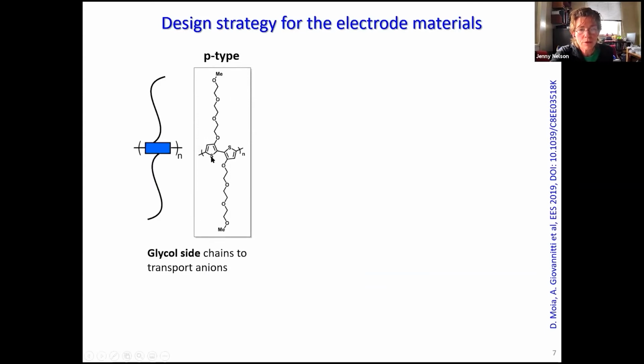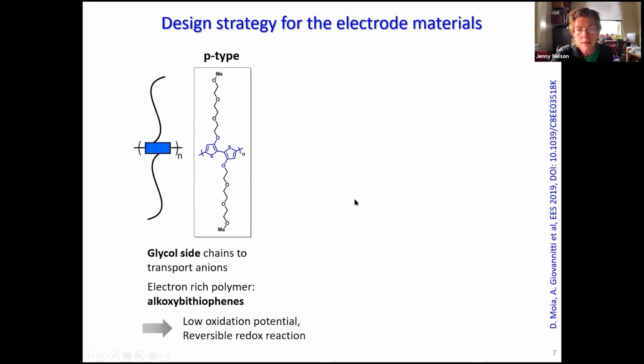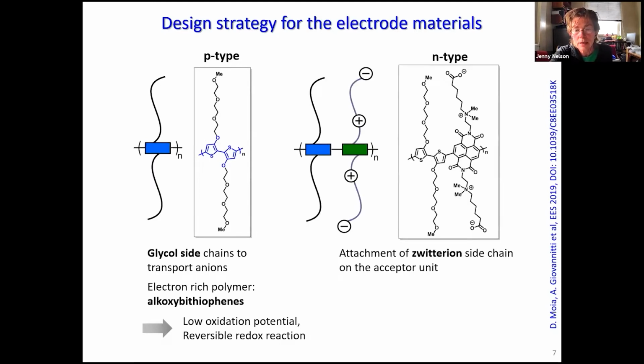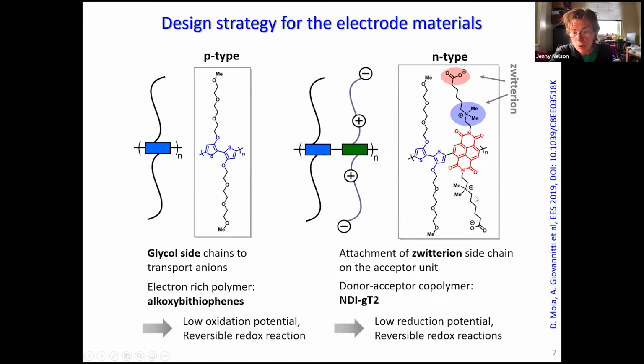The p-type that we used is quite widely used in this field, a bithiophene, an oxybithiophene with alkyl side chains. It's electron rich, so it's relatively easy to oxidize, and it has nice reversible redox properties. And for the n-type, we used a version of the NDI-T2 copolymer that has both glycol and zwitterion side chains, so two different types of polar side chains. The NDI-T2 is known to be relatively easy to reduce and also to show reversible redox properties. So these were the two polymers that we did the majority of our first work with.